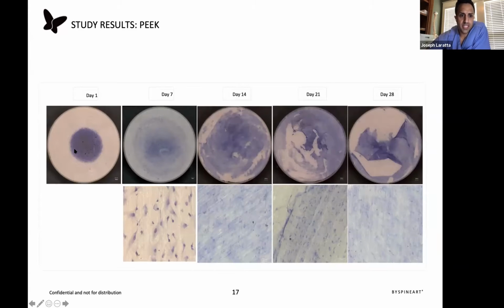At day 1, this is the aliquot of mesenchymal stem cells that were placed on the PEEK or plastic disc. As you can see at day 7, it forms a relatively confluent layer, but sometime between day 7 and day 14, the layer starts to break and fragments, and the cells become detached from the PEEK itself. So there's something about cellular adherence to PEEK that early on, there may be some dispersion, but later there is no significant integration of the cells with the plastic itself.